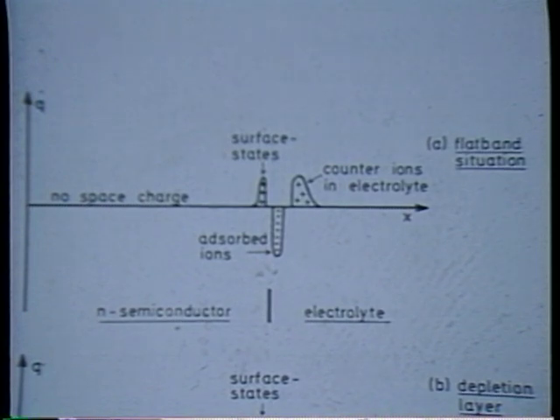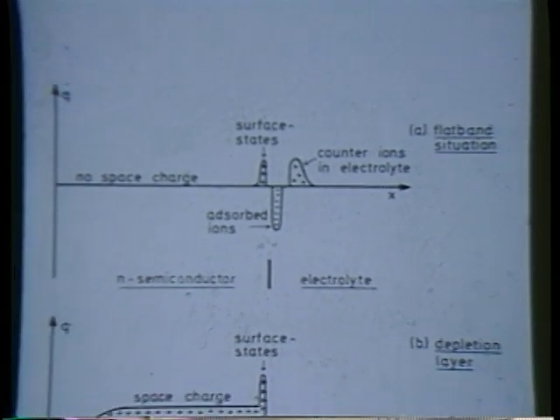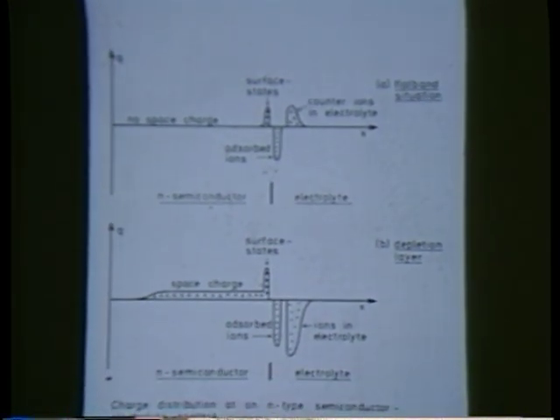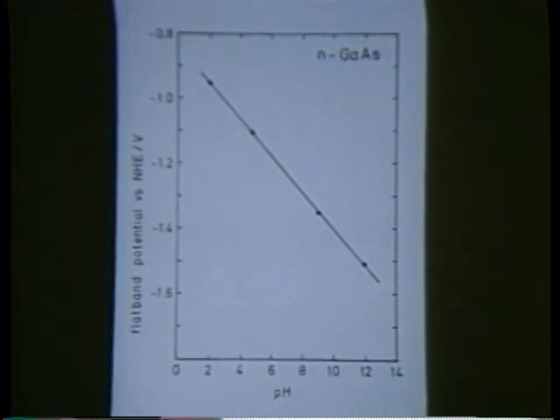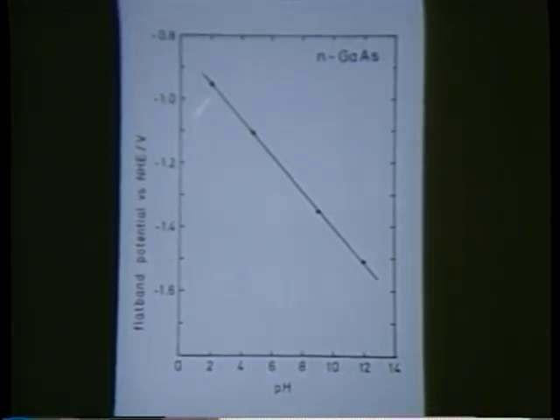Now, in rare cases, a surface behaves so uniformly as that which I showed you for tungsten selenide. Tungsten selenide is a layered material, and you can really produce a very smooth, ideally smooth surface. If one does such experiments with gallium arsenide or gallium phosphide, on first look, you would not expect that the position of the flat band is pH dependent. However, it is a common feature that it is so, and that means that obviously the surface has a different chemical composition. It has obviously some oxide layer, maybe only a monolayer of chemisorbed oxygen, and this surface interacts now with water, with the pH, and makes this pH dependent. That's a very common feature.